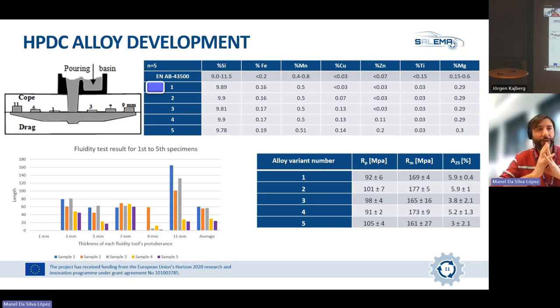Then what we have also done is to create high performance, high-pressure die casting aluminum alloys more robust to this scrap, so that they can be produced more easily with a high amount of scrap. So we have analyzed the actual effect that impurities have on a high performance aluminum alloy, the most typical being EN AB 43500, an aluminum silicon 10 magnesium alloy. What we have done is increase the level of copper, which according to the standard should be below 0.03%, zinc, and also iron.